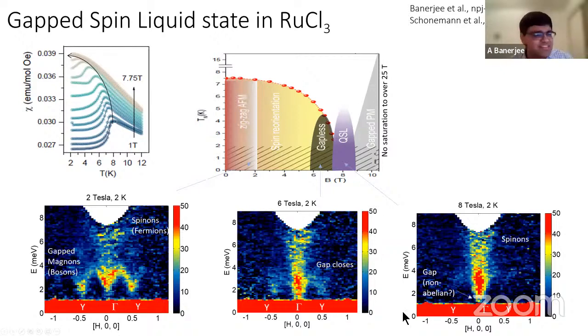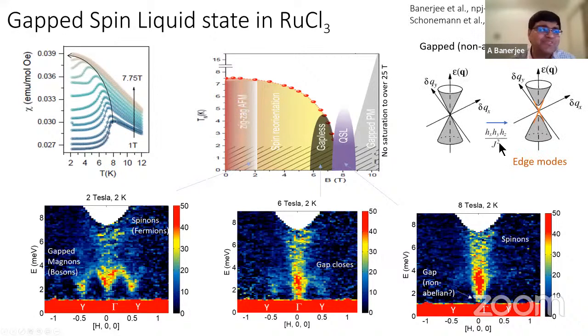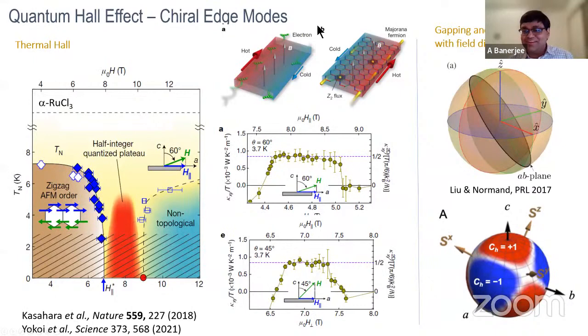And what really happens is that we start to see a tiny gap coming up right at the gamma point. Now, you can't help but ask the question: is that really the gap we are looking for here? Wow, is that really the gap? And should we see these edge modes? So when we published this result, there was a group in Japan which went ahead and looked at the thermal Hall effect. And lo and behold, what they found is that you indeed see a very robust half-quantized fractional quantum Hall plateau in thermal transport and thermal Hall effect in this material right at this 8 Tesla state.